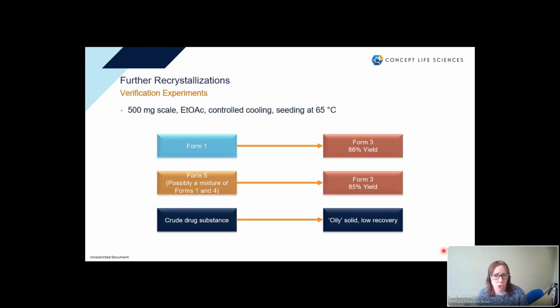We then wanted to do slightly larger experiments. We didn't have loads of material left, so these were half-gram experiments. And we used what we sort of considered to be our best theoretical conditions. We used ethyl acetate, we used a controlled cooling curve, and we seeded at 65 degrees C, which at the concentration we were working at was approximately 25% into the metastable zone. So we took forms 1 and 5 and put them through our best conditions. And you can see that, as expected, at this point, we've got form 3 in quite a nice yield for a final recrystallization.